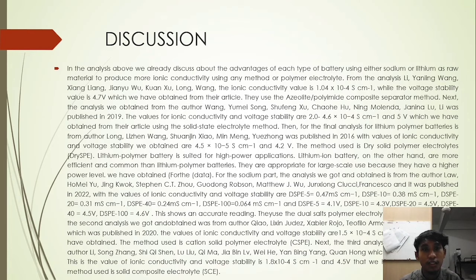For discussion, in the analysis above, we already discussed the advantages of each type of battery using either sodium or lithium as raw material to produce more ionic conductivity using any method or polymer electrolyte. From the analysis by Li Yanling Wang and his friend, the ionic conductivity obtained is 1.04 times 10 to the power of negative 4, while the voltage stability value is 4.7 volt, which we obtained from their article. They use a zeolite or polymer composite separator method.